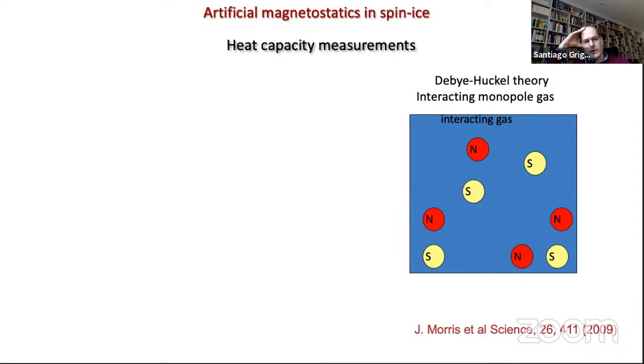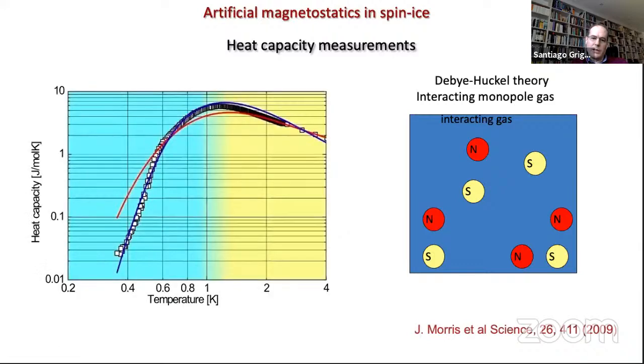So one of the nice things about this is that now not only can you describe your ground state, but you can describe excitations. And because your system is formally identical to a system of charges, you can borrow results from other areas, for example, from electrolyte theory, and use it for spin ice. So here, for example, what we're saying is that you can take now the Debye-Huckel theory and calculate the specific heat for spin ice, right? You just replace the electrical charges by these magnetic charges, and you use exactly the same formulation.